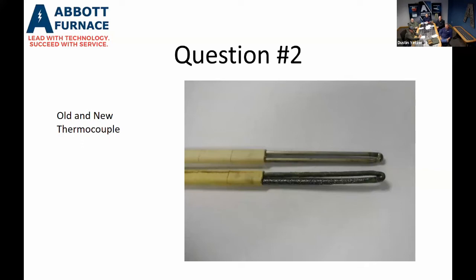Some of the expensive thermocouples like the R's and the S's can be sent back in to be recertified and get a recertification with them. But if you have type K's in your furnace, that's the picture here, they're pretty much a throwaway thermocouple once you use them. The picture shown here is what happens with a type K thermocouple after about 3 months of use in a furnace that's running at 2050. This is what they call the degradation of the thermocouple, or drift, if you will.